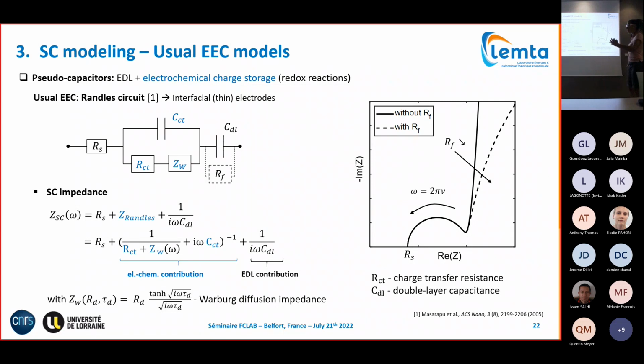Charge transfer resistance represents the kinetics of your redox reaction. The capacitance means the capacity of your pore space to store charges. And in order to take into account ion diffusion inside the electrode pores, you connect a diffusion impedance in series to the charge transfer resistance. And the most classic diffusion impedance is Warburg diffusion, which is pure diffusion.